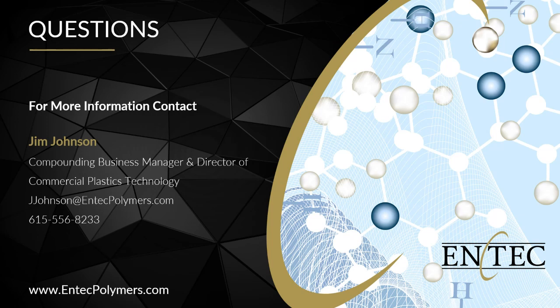Let's see. What compatibilizer do you recommend for blending PVOH-based polymer with polyethylene? Once again, for this application, a maleic anhydride modified compatibilizer is what you would need. The maleic anhydride reacts with the PVOH, and the olefin backbone is compatible with polyethylene.